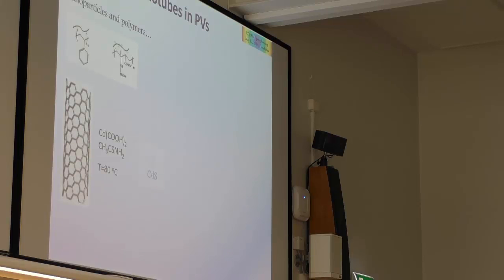And of course, this is not always limited to chemistry, but you can be really clever and use different things. So let's take an example of a polymer. You have polystyrene, which is a hydrophobic molecule, and you have a hydrophilic polymer. So if you're a good polymer chemist and you make a block copolymer comprising a hydrophobic and a hydrophilic part, then you can introduce this copolymer onto the carbon nanotube.